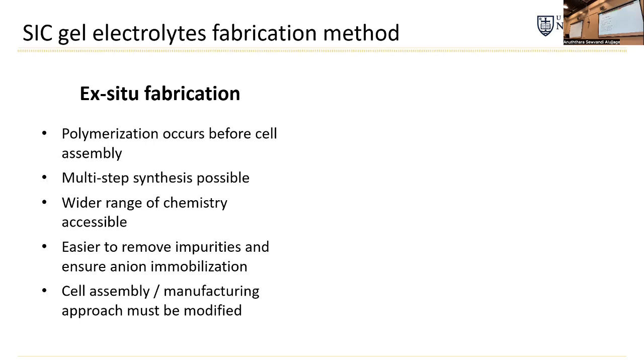And then we carefully characterize our products. And as I told you, for one of those polymers I pointed out in the literature, we often use multi-step, expensive synthesis routes because we can, so we can make very novel materials. The other benefit of this is when we make a material and we purify it, we know we remove the impurities, so that won't affect your electrochemistry. But the whole problem with this is if you're going to actually apply these materials in real devices, we totally have to change the battery cell assembly and manufacturing processes.